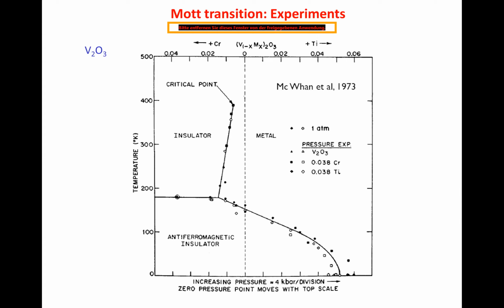If you look at this condensation energy defined that way, which is a little bit artificial in some ways, because this normal state is not the stable state, you find that on one side it's controlled by... there's a crossover, all the way down to zero temperature. If I ask what is the condensation energy, the difference between the energy of the ordered state and the not ordered state, you see that on one side it becomes antiferromagnetic because of potential energy, and on the other side because of kinetic energy. So that's a crossover from that point of view.